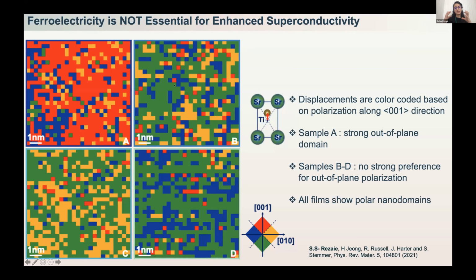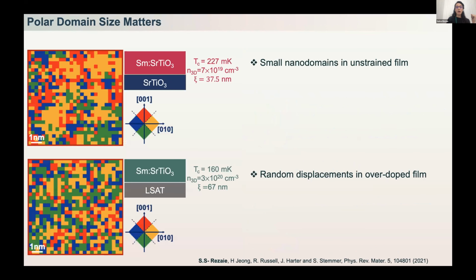We still have domains, we still have these correlated lattice distortions in the structure, but it might be that the ferroelectric domains are not strongly oriented along the 001 direction, but we still have a very similar length scale of these domains forming in the structure. But how about the films that don't show this enhancement in superconductivity, whether these domains are still forming in the structures? For that, we looked at the films that are grown on strontium titanate, and also the films that are not strained, but rather have large carrier density.